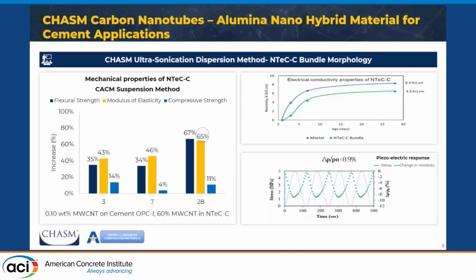The NTeC-C bundle was better in compressive strength and also in flexural strength. However, we hit the goal with this NTeC-C bundle to achieve a level of piezoelectric response higher than 5%. We obtained 8.9%. That means this material can be suitable for applications related to smart concrete.